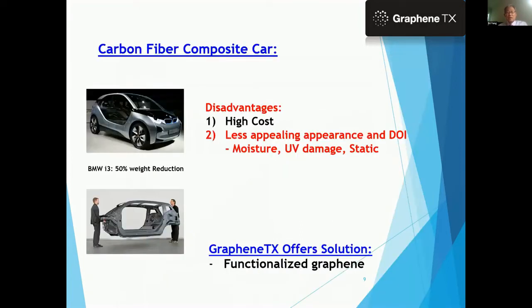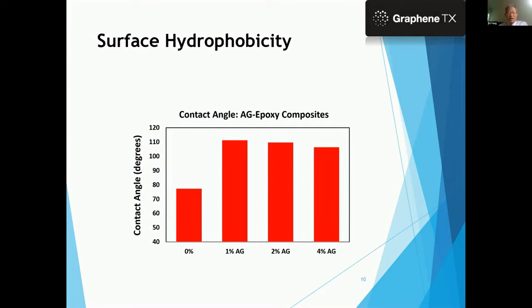So as you can see, we can handle the high cost problem. But the second problem, the reason why it has a less appealing appearance as well as a poor depth of image, is due to moisture. Composite, compared to metal, loves to absorb moisture, and also polymer has UV sunlight damage, and also polymer is not conductive, so they are static. So I will show you we can alleviate some of this problem, or we can solve this problem. We need to develop lots of data, but I'd like to show you the preliminary data. As you can see, if you add just 1% aminated graphene epoxy, you will see an increase of hydrophobicity.